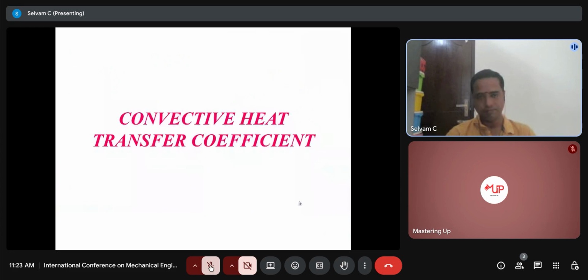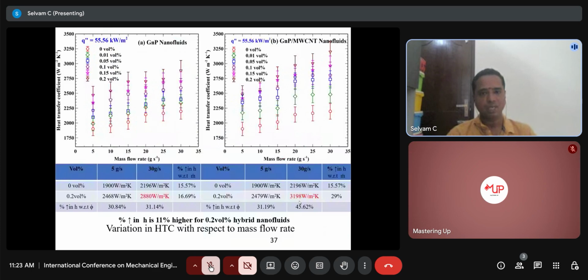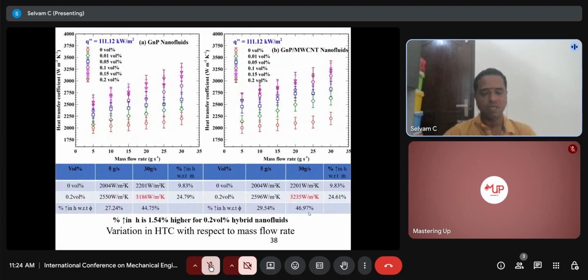At the same time, we can see the convective heat transfer coefficient. It is also increasing with respect to the mass flow rate, and while increasing the nanoparticle concentration, it has increased significantly. With respect to graphene we got 31.14 percent, and with respect to the hybrid, 45.62 percent. While increasing the heat flux, it has increased with respect to the GNP concentration up to 44.75 percent, and while using the GNP multi-wall carbon nanotube hybrid nanoparticles, up to 46.97 percent.